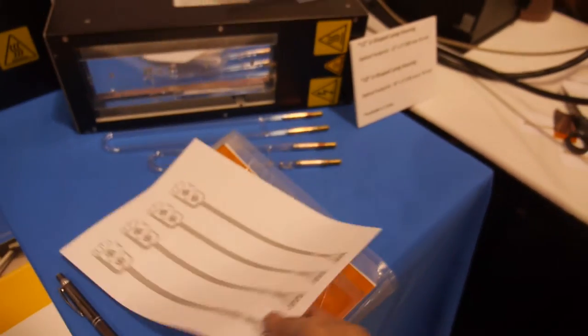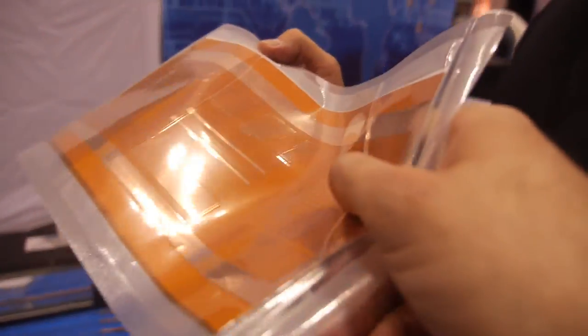The way people make Blu-ray discs is also going to translate to the way people are making flexible electronics — very similar challenges. The advantage that pulsed UV brought to the Blu-ray disc market is the ability to deep-cure into the disc through multiple layers without burning off or overheating the top layers. That same knowledge translates into printed electronics, where you want to sinter metal on TPU, PET, or paper and drive down the resistivity without burning the paper or shrinking the TPU.